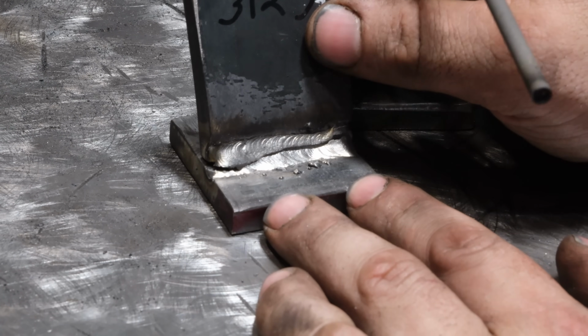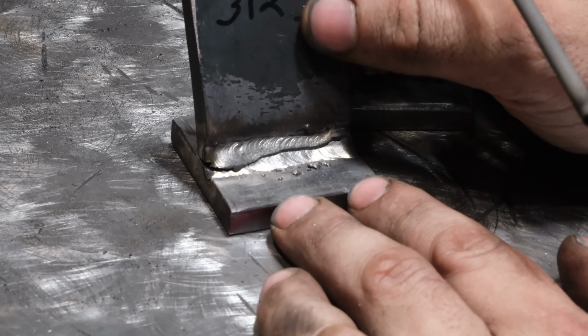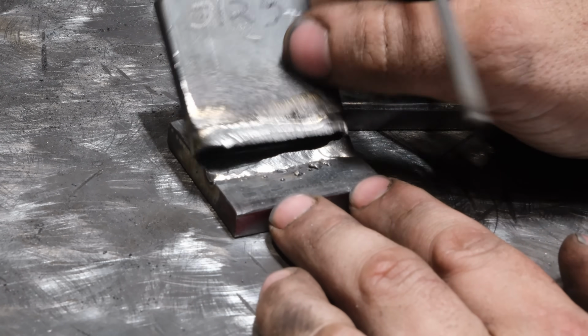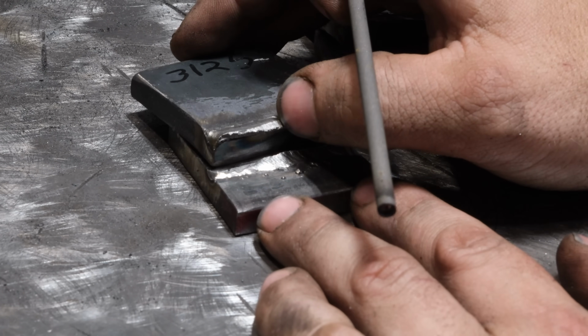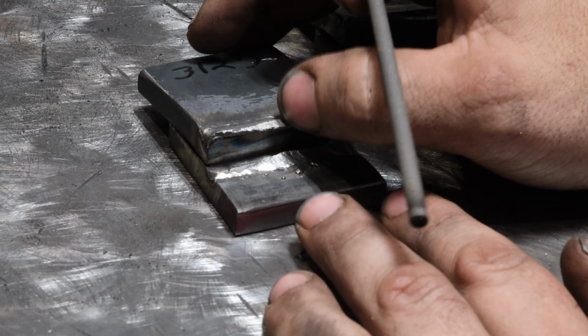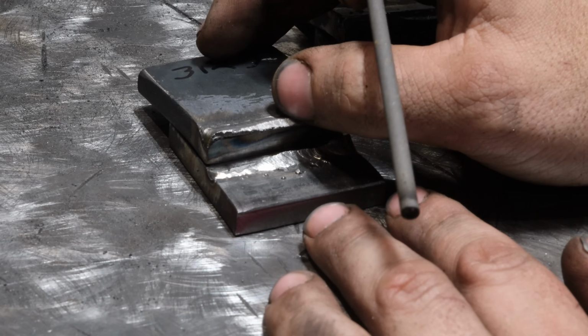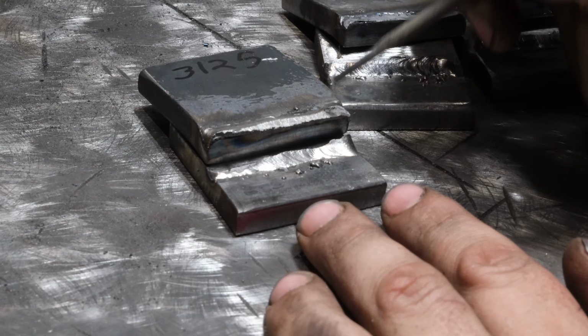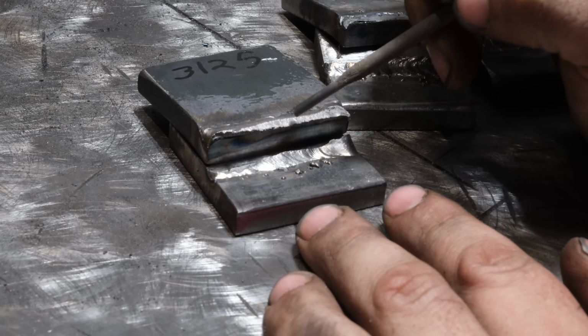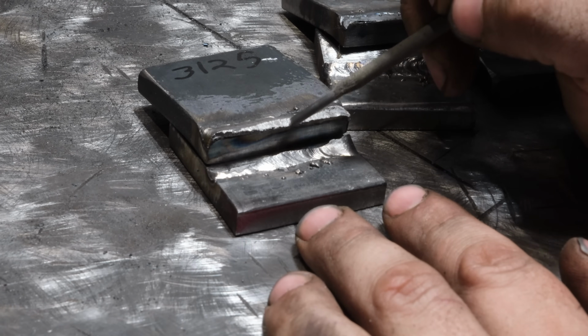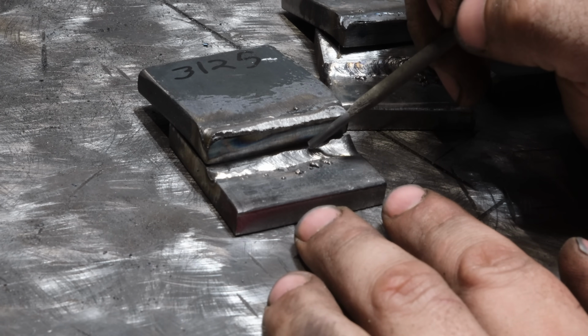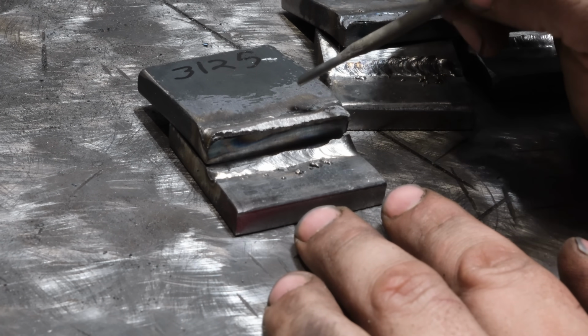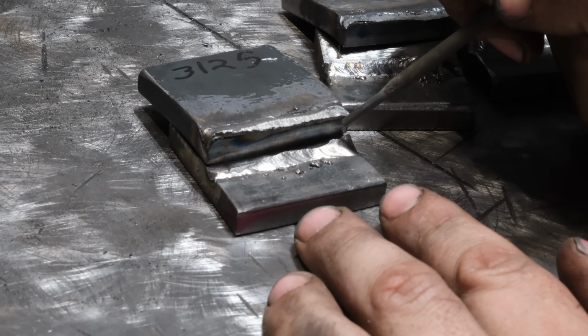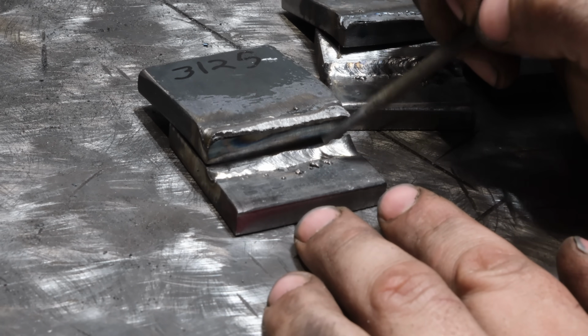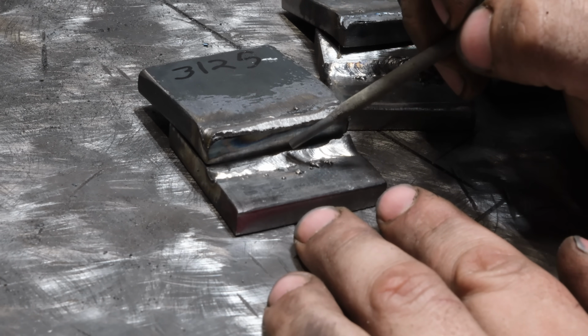I've done a lot of testing on 309 rods off camera for jobs and projects that I had to do, and this is going to perform similar, and it's not likely to fully bend before something fails. And a lot of that, believe it or not, isn't because of the strength of the material of the weld. It's actually pretty high in tensile strength. The issue is 312 stainless generally deposits very thin welds, and it has very poor penetration.